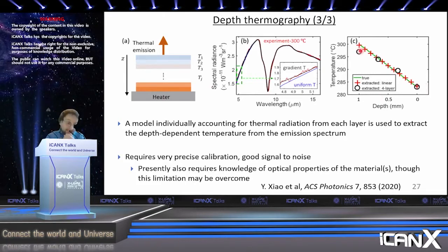Now, I should say that even though this is a very compelling and interesting technique, it does have significant drawbacks. So it requires this very precise and careful and accurate calibration that I talked about before. It also requires a system that has pretty good signal to noise and requires knowledge of the optical properties of the materials. Although I think this limitation can be overcome by, for example, doing these measurements as a function of angle and as a function of polarization, and doing something akin to spectroscopic ellipsometry, where you're getting more and more information about the sample because you have more degrees of freedom in your measurement. So I think some of these issues can be overcome.